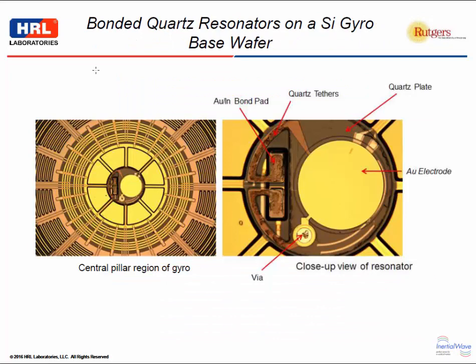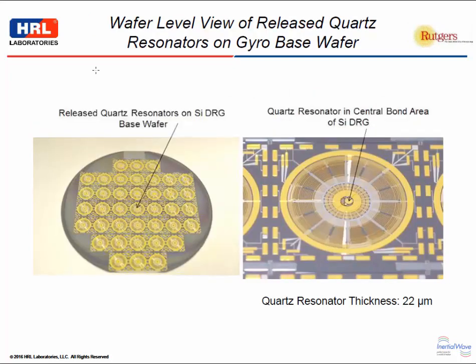This then shows the integrated quartz devices on the silicon base wafer. You can see these are the gold indium bonds. They had to survive up to the 360 or so bond for the silicon device in a subsequent step. This is the vias within the thick quartz, taking the top metal down to the bottom bond metal. And this is just a lower view, a picture of the entire wafer. So these are all the devices bonded to the base wafer, and you can see the quartz resonator right there.